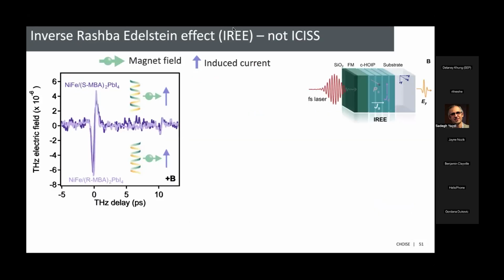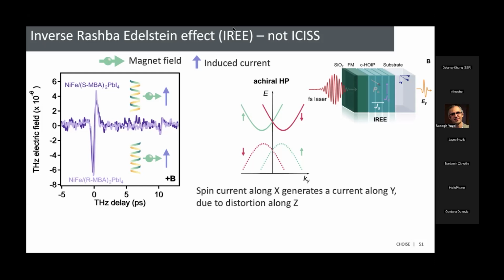All right, pretty cool. So what Efon did here, the spin is oriented in the plane. She shines this in, you get a spin current injected with its orientation in the plane, and she's going to measure the charge current being generated in the perpendicular direction, the Y direction. And there, that's what you see. And when she changes the polarity, nothing changes. It stays the same, but you have this ultrafast current being generated. That's because this is due to the inverse Rashba-Edelstein effect. So you have spin splitting in your bands in these systems. And if you inject spin-polarized carriers along the X direction into, say, one of these bands in the K direction, it picks up some velocity in the Y direction. And if you reverse the spin, then it goes in the other direction. It's not dependent on the chirality. It's only dependent on the in-plane distortion.